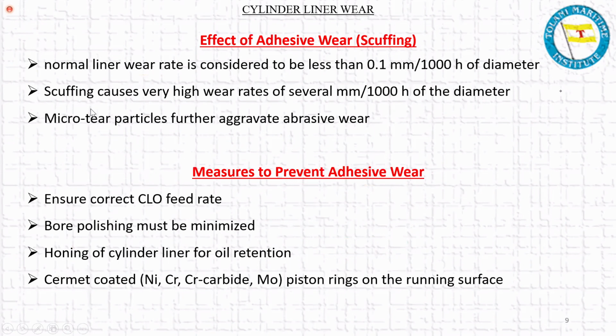What is the effect of adhesive wear? The normal liner wear rate is considered to be 0.1 mm per 1000 hours of diameter. So diametrically, the liners are supposed to be reducing 0.1 mm every 1000 hours, normal wear. But if macro scuffing or macro wear, adhesive wear, is taking place, it can reach several millimeters per 1000 hours. It can reach 2, 3, 4, 5 millimeters per 1000 hours.